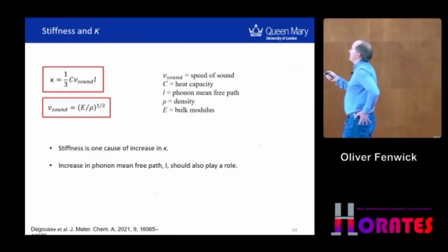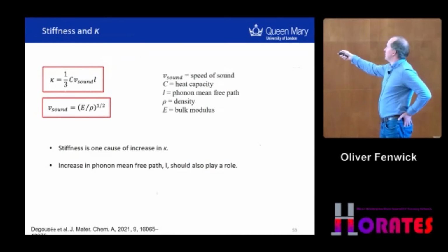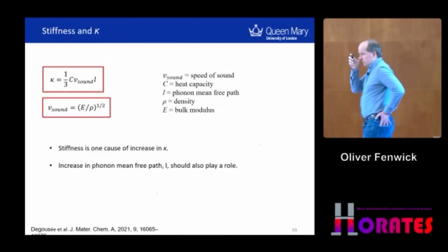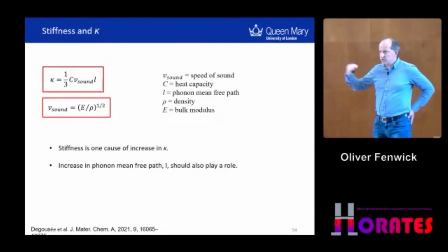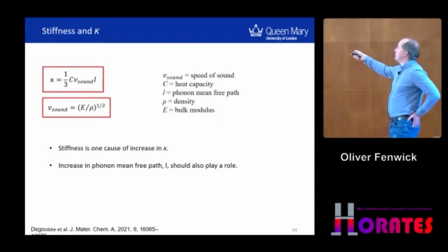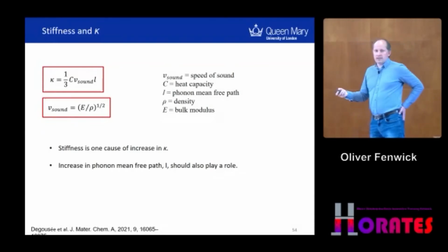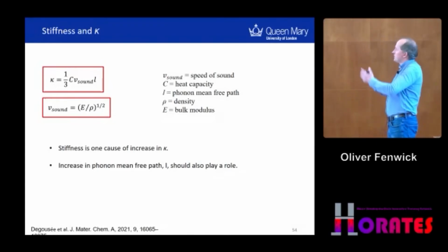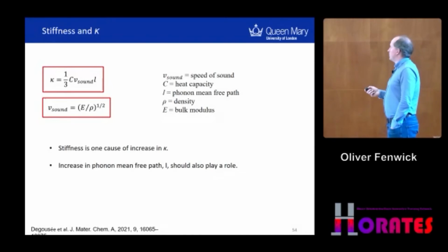I just wanted to point out that in some classical theories of thermal conductivity, the thermal conductivity is proportional to the heat capacity, the speed of sound in the material, and the phonon mean free path. The speed of sound is proportional to the square root of the bulk modulus. So if you see an increase in modulus, you should see an increase in the speed of sound, and if everything else is the same, an increase in the thermal conductivity. On the other hand, it's a square root, so it's not a very strong relationship, and this alone can't account for the increase in thermal conductivity of our film. So maybe there's an increase in the phonon mean free path as well, which might be related to some more intimate aspects of the morphology.